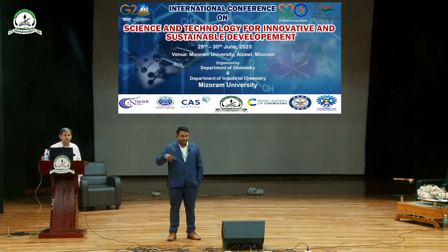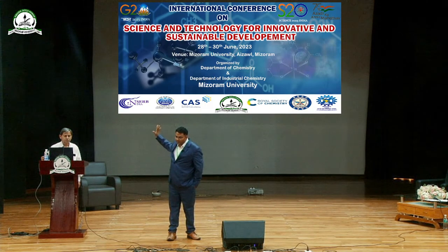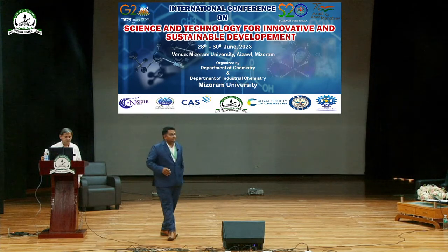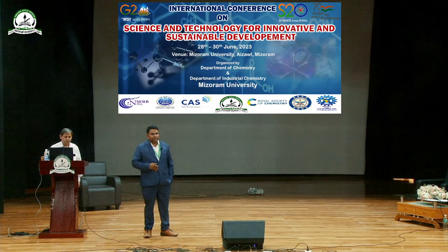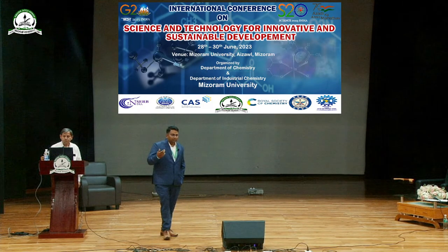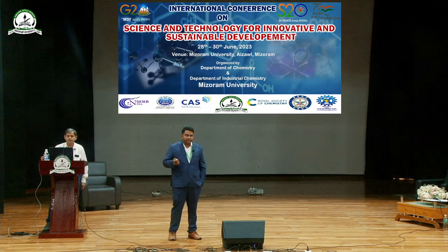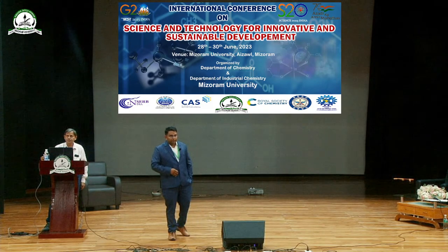We later studied this, whatever work I have shown so far, we worked on that also. What we found is that the role of base is very important. When we increase the base, even the noble metal catalysts show much faster kinetics for the decomposition of hydrazine into nitrogen and hydrogen.